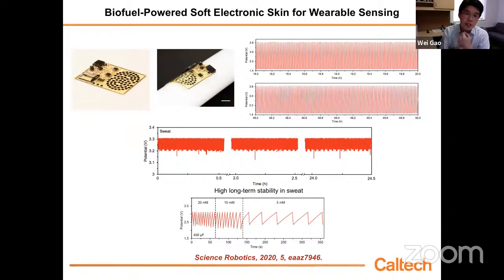We can wear this at different body parts for continuous operation. And we do the charging, discharging. We have a small capacitor. We can charge this capacitor by harvesting the energy from the biofuel. Charging, discharging for the first 20 hours, you see up to 50 hours, still the performance is the same. This system can continue to work. And if we use sweat even for 24 hours, you see, they can still have very stable performance. Even though sweat contains almost a minimal concentration, 5 millimolar lactic acid level, the system can still work very well. Again, the entire system is battery free.